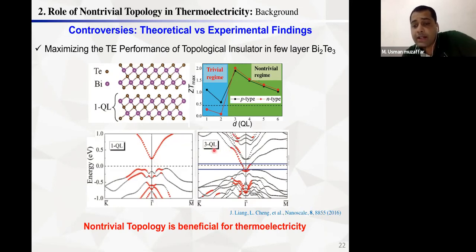So they found that if we consider three quintuple layers, this system is topologically non-trivial. You can see that there is a Dirac cone type behavior. You can see that there are gapless surface states. Then they calculate the transport properties, and they found that in the trivial regime, one quintuple layer and two quintuple layers, the maximum ZT is 1. But in the non-trivial regime, the maximum ZT is 2. So this paper supports that non-trivial topology is good for thermoelectricity.